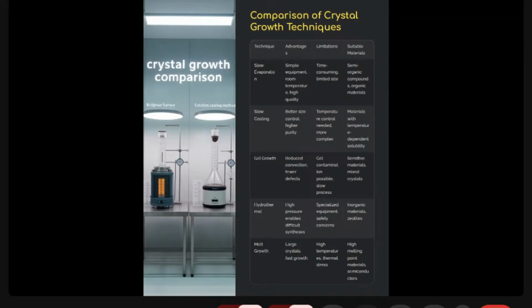The next method is the slow cooling method, in which a hot saturated solution is gradually cooled, causing solubility to decrease and crystals to form. The advantages are that it offers better control over size and high purity of the crystal, as solute molecules slowly arrange themselves into the lattice. The limitation is that it needs precise control of temperature. If there is any deflection, we can get multinucleation and crystals cannot be formed. Next is hydrothermal synthesis, a technique employed under high pressure and high temperature within a sealed autoclave. Its advantages are that it allows very high quality crystals and enables crystallization of low solubility inorganic crystals.